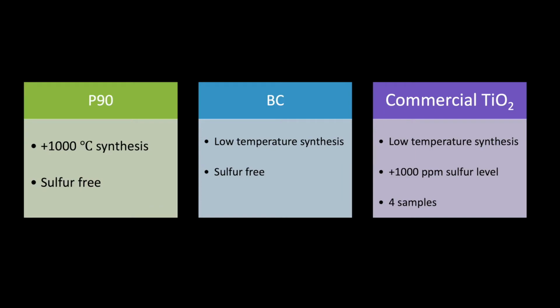In this study, we looked at two pure titania materials, P90, which is synthesized at high temperature with low defect density, and homemade pure low temperature synthesized anatase, which has higher defect density. For sulfur-containing material, we use commercial anatase from 4 different vendors. The sulfur content in this material was over 1000 ppm.